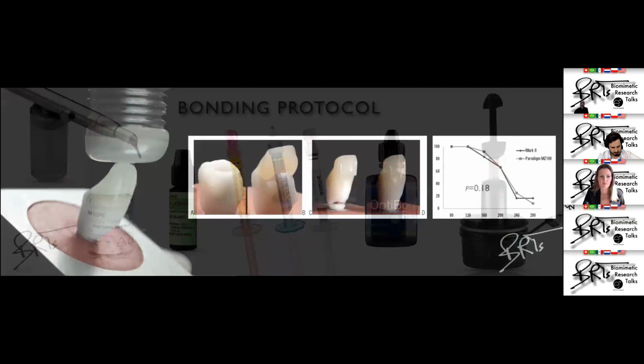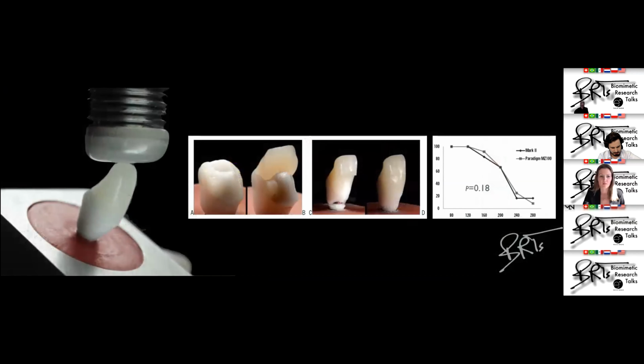So once the sample was ready, finished and polished, they waited 24 hours and then they loaded it in the fatigue MTS machine, 280 newtons, a total of 140,000 cycles.